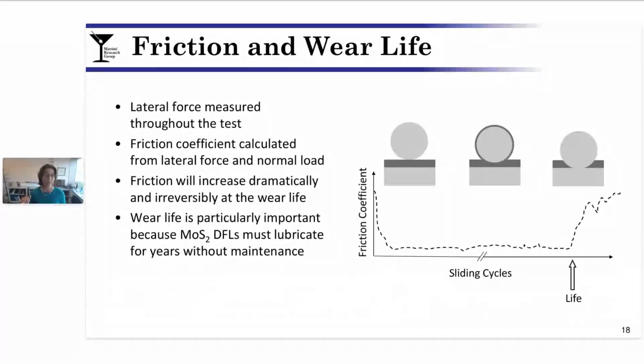And then at some point, the friction again increases rapidly. This is associated with loss of the dry film lubricant in the wear track and is referred to as the wear life of the coating. Wear life is often more important than friction in space applications, because once the wear life is done, the component is also done. Therefore, the life of the lubricant can determine the life of the coating.